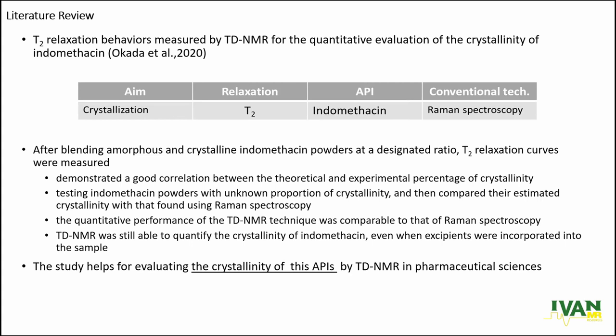They tested indomethacin powders with unknown proportion of crystallinity, and compared their estimated crystallinity with that found using Raman spectroscopy. The quantitative performance of the TD-NMR technique was comparable with the conventional technique. They also state that TD-NMR was still able to quantify the crystallinity of indomethacin even when excipients were incorporated into the sample. So they conclude that the study helps in evaluating the crystallinity of APIs by TD-NMR in pharmaceutical